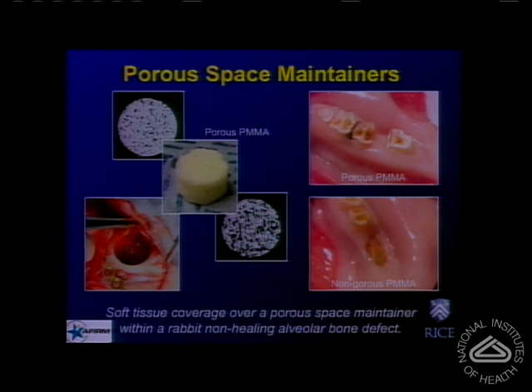So here you can see the results of the implantation after 12 weeks. In the case of porous polymethylmethacrylate, we saw enhanced healing as shown here. However, in the case of the non-porous polymethylmethacrylate, we have extrusion of the implant and wound dehiscence. So obviously this is a case of failure. This is a case of success.